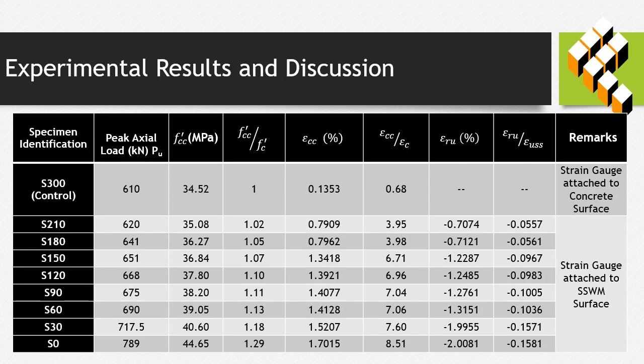From the experimental results, it is found that as the gap between the SSWM strips is increased, there is a noticeable reduction in the axial and circumferential stresses and strains in the wrap region. A strain softening response is observed when the gap between the strips is lower than the specimen diameter, signifying sufficient confinement and ductile behavior. When the gap between the SSWM strips is beyond the specimen diameter, the effectiveness of confinement becomes negligible.